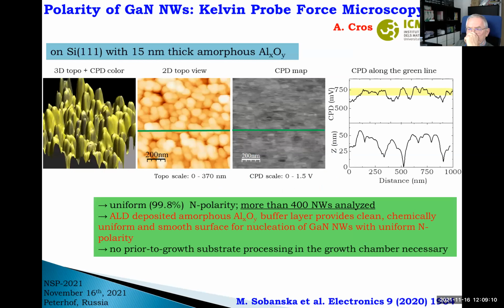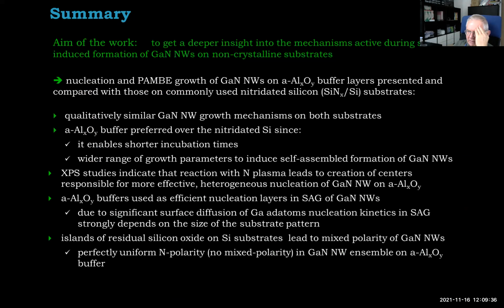Okay, and a very nice message for us. If we use amorphous aluminum oxide on top of silicon without any special preparation, we just get a perfectly uniform polarity, nitrogen polarity. More than 400 nanowires were analyzed. All of them were perfectly nitrogen polar, so no mixed polarity at all.